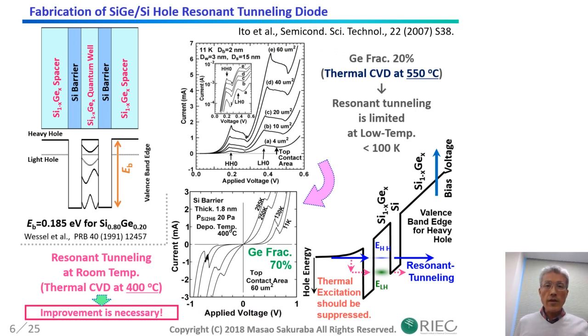As another kind of quantum effect devices, we have fabricated resonant tunneling diodes. Negative differential conductance is attractive for realizing new functions by fewer devices in electronic circuits. For lower germanium fraction heterostructure, it was difficult for us to achieve room temperature observation of current peak. However, by increasing germanium fraction above 50%, such as 70%, we have succeeded in room temperature observation of current peak. Unfortunately, the peak was so small, and this result is still far from circuit application.